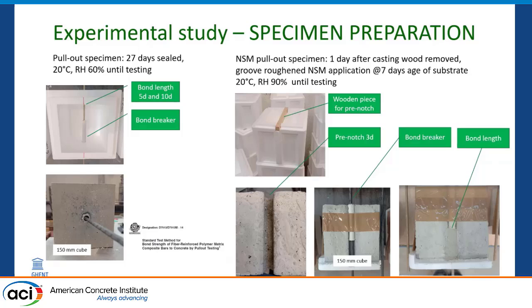Here you can see the specimen preparation. For pull-out specimens, we used polystyrene molds with bond breaker and embedment lengths of 5 and 10 D. For near surface mounted, we used also 150 millimeter cubic molds made of polystyrene and wooden pre-cuts for creating the groove. After 1 day with mortar specimens, we roughened the surface of the groove with a steel brush, and 7 days after casting, we applied alkali-activated and Portland cement mortars together with the rebars, and we waited for 28 days from the mortar application to test these specimens.